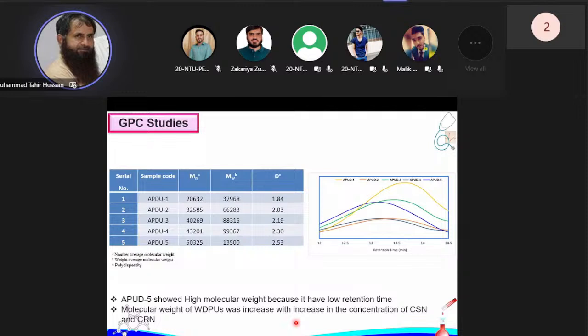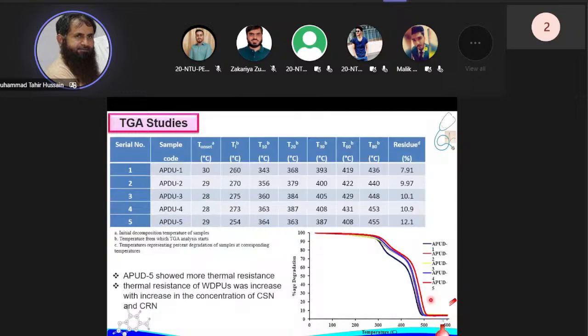And also it has been observed that the thermal resistance of the polyurethane has been increased by increasing the concentration of chitosan and curcumin. This red line is of the aqueous polyurethane dispersion containing the highest concentration of chitosan and curcumin, which shows the maximum thermal resistance as compared to the other materials.